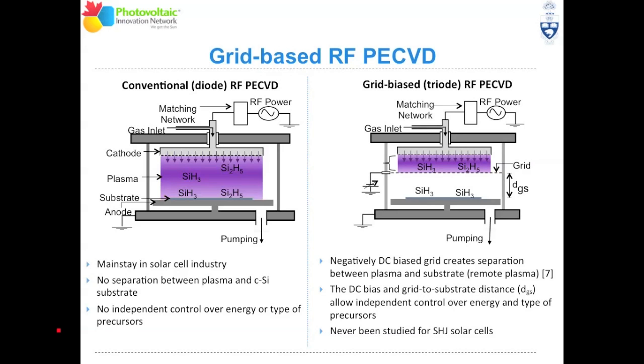What we did is we applied a method known as the grid-biased triode RF PECVD process. And this method is just a simple modification over the conventional diode PECVD. The only major difference here is you're adding in a DC biased grid. And this DC biased grid confines the plasma between the grid and the powered cathode. So now your plasma region is separated from your growth region. Your crystalline silicon substrate is not exposed directly to your plasma. And by modulating the DC bias and also the distance between the grid and the substrate, you can control the energy and type of precursors that are involved in the silicon growth.